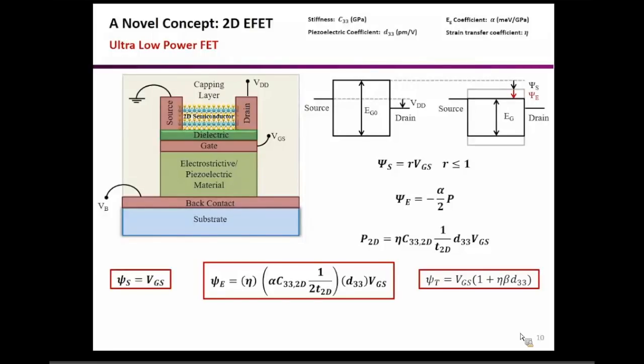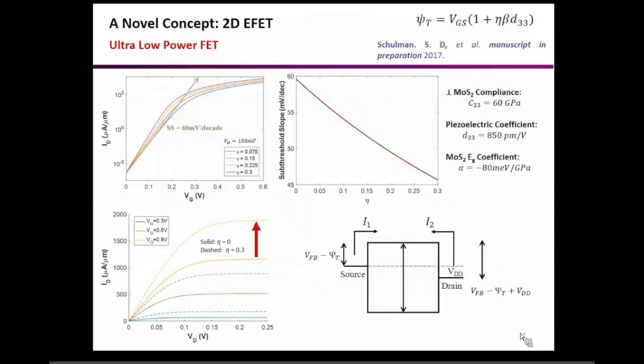And this additional band movement is proportional to whatever pressure I can generate, the out-of-plane strain I can generate, which is again proportional to the gate voltage applied and whatever the piezoelectric material is. If I choose a piezoelectric material with a large piezoelectric coefficient, where the movement will be larger, I will create larger stress. Okay. But now the important part is that the total band movement becomes more than my applied gate bias. So I am having an internal voltage amplification. And this internal voltage amplification is something that's going to reduce the subthreshold slope below 60 millivolts per decade.